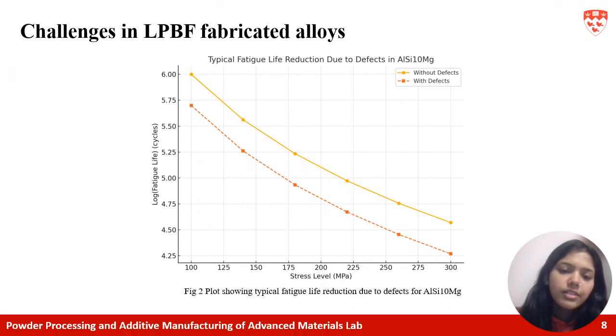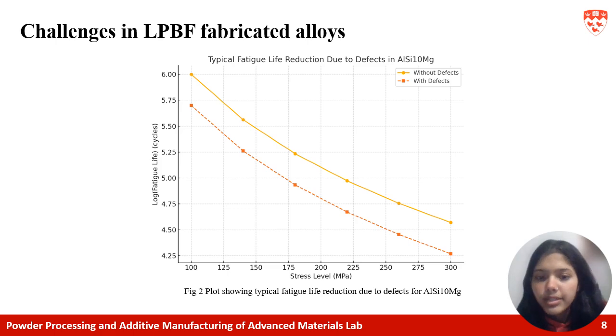Moving on to the other challenges in LPBF-fabricated alloys, here is a graph which illustrates the difference in fatigue life between specimens with and without defects. So notice how the fatigue life drops significantly due to even small defects. That's because stress concentrations amplify crack growth, leading to earlier failure. This graph perfectly underscores the importance of minimizing defects during manufacturing to extend a component's lifespan.